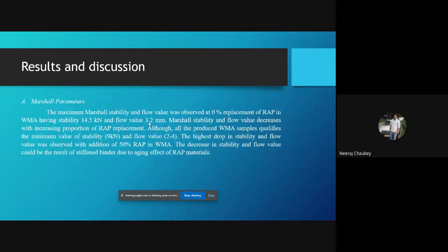These are the results of the Marshall parameters. The maximum Marshall stability and flow value was observed at 0% replacement of RAP. This means when we have 100% natural aggregate, it shows the maximum stability and flow value.